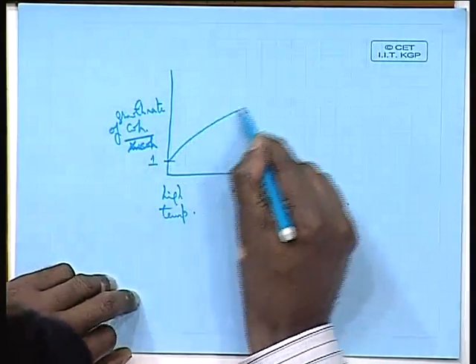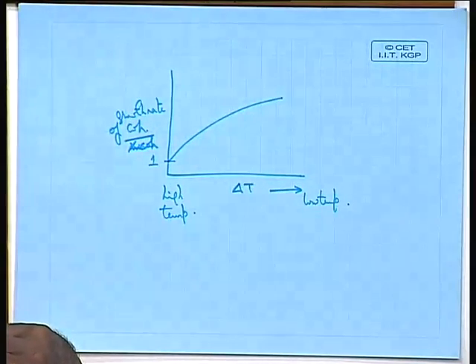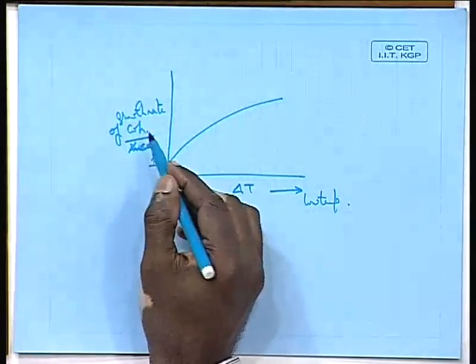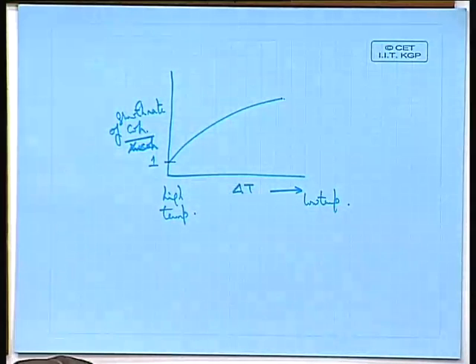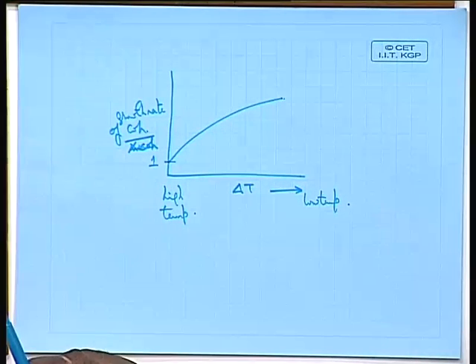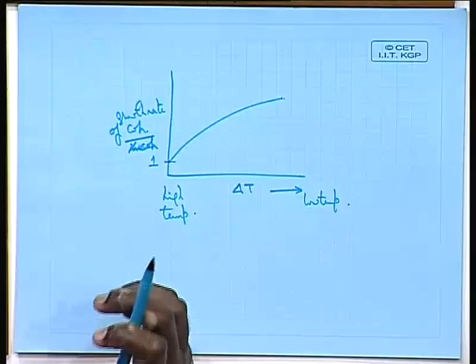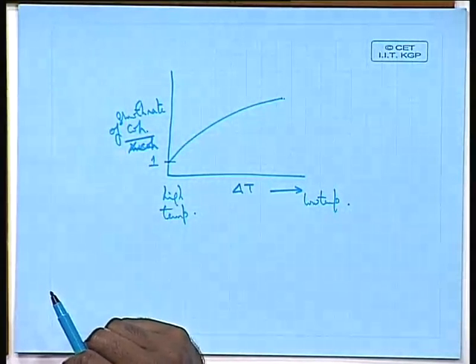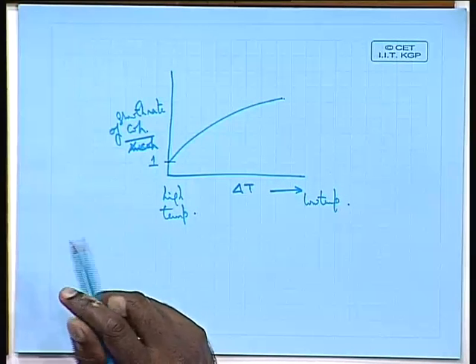So if you try to plot, you will get this kind of a situation. The tendency for the formation of coherent precipitates is much higher at high undercoolings, and when you come to low undercoolings, which are very close to the transformation temperature, you have a greater tendency for the formation of incoherent grain boundary allotriomorphs. That means the precipitation occurs near the grain boundaries, not within the grains, and then the growth occurs into the grains, and the morphology of the precipitates will be more or less spherical, not really acicular. And they more or less grow in a symmetric fashion into the grain, in a spherical kind of a situation.